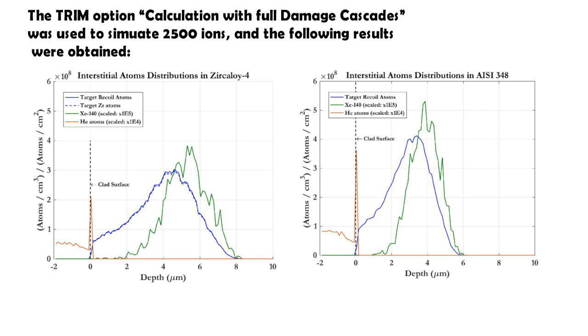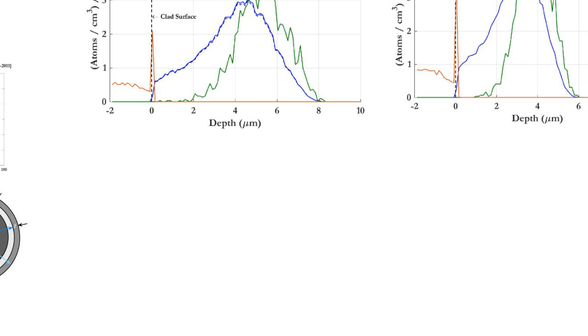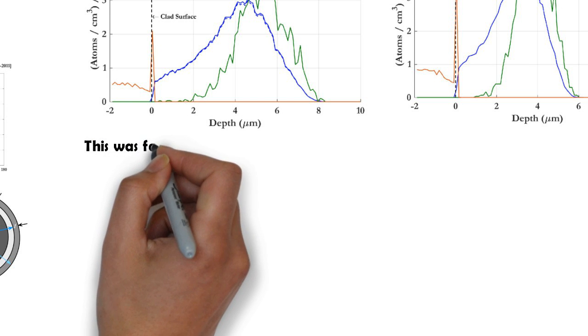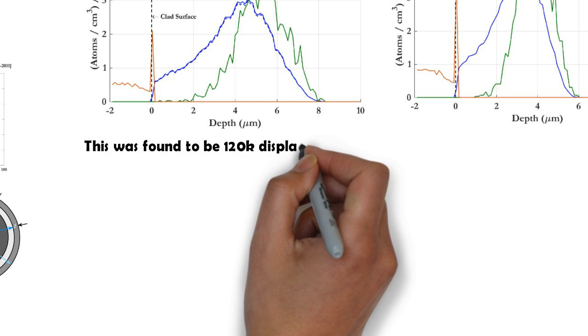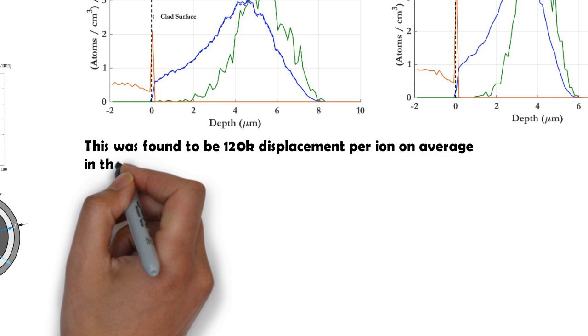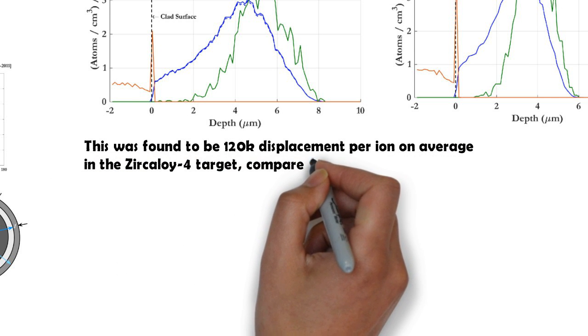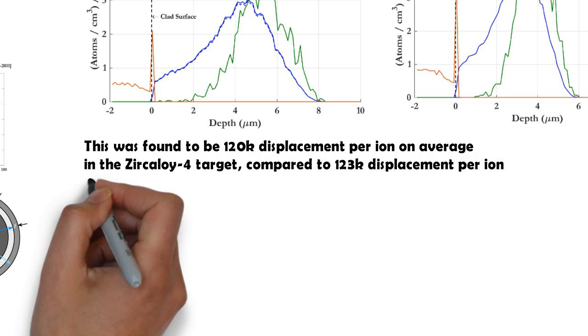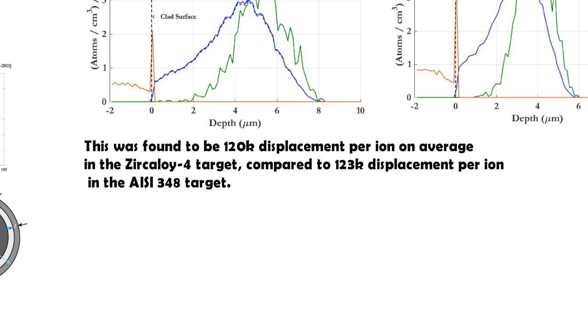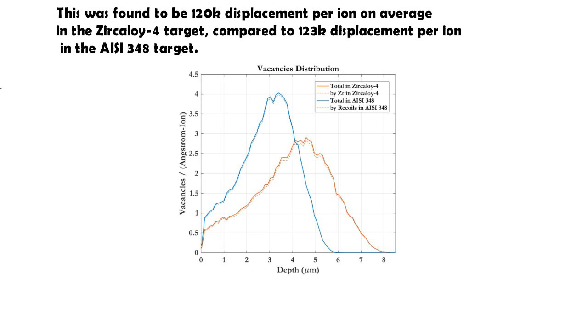The area under the blue curves is the number of interstitial atoms per ion, which is almost equal to the number of displacements per ion. This was found to be 120 K displacements per ion on average in the zircaloy 4, compared to 123 K displacements per ion in the stainless steel target. Also, the distribution of vacancies shows agreement with the distribution shown above.